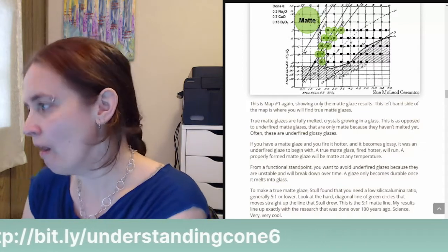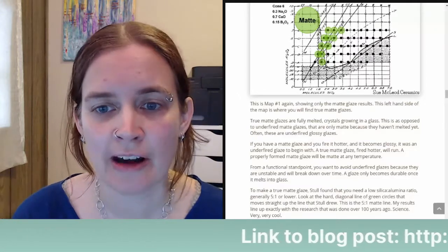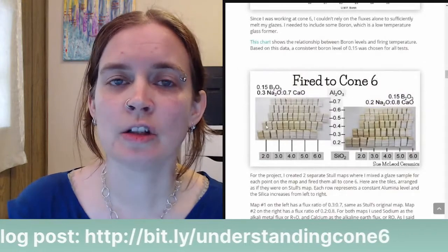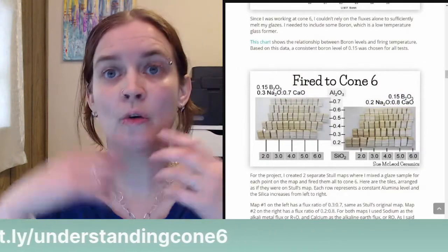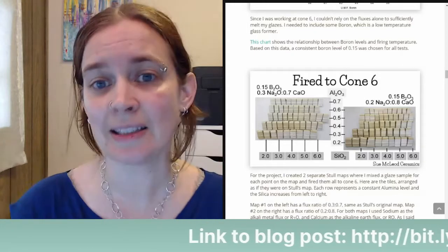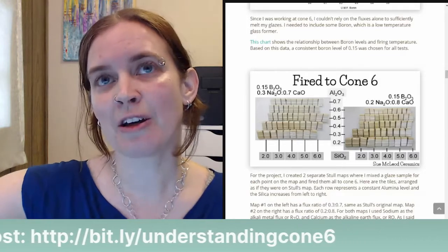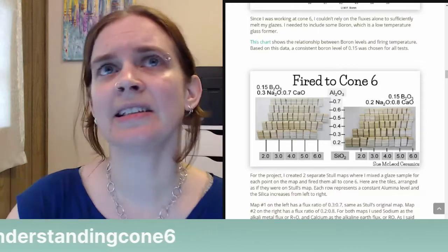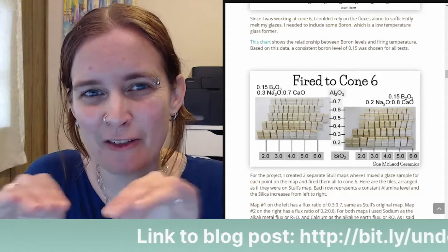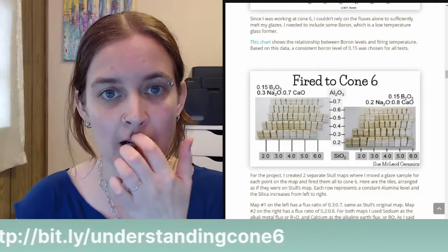So basically, I think I started with 200 grams. So when I made the very first tile on the left, I started with 200 grams of glaze. So you have to make sure that you're mixing your glaze really well. So before every dip, I would mix the base glaze, I would sieve the glaze, dip a test tile, then I would sprinkle silica on the top. I didn't sieve every time. What I found is if I sprinkle the silica onto the layer of water that's on the top of the glaze, then it just slakes down. But I always use a high-speed mixer in between.